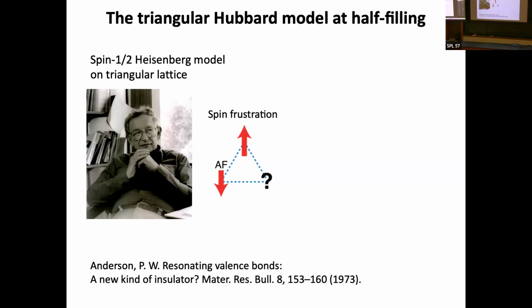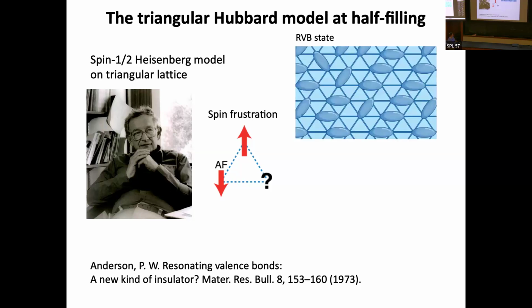And so if you put antiferromagnetically coupled spins on the triangular lattice, the key thing that happens is, of course, you can put the first spin, let's say up, the second spin you want to point down, but then you're not sure what to do with the third spin, right? So this is the phenomenon of spin frustration. And Phil's idea to find a ground state in this Heisenberg model was maybe what you want to do is to pair up these spins in a spin singlet and then cover the entire lattice with these singlets. But there's no reason to pick a particular covering, so maybe what you want to do is create a superposition of all these coverings. And that's what he called a resonating valence bond state.